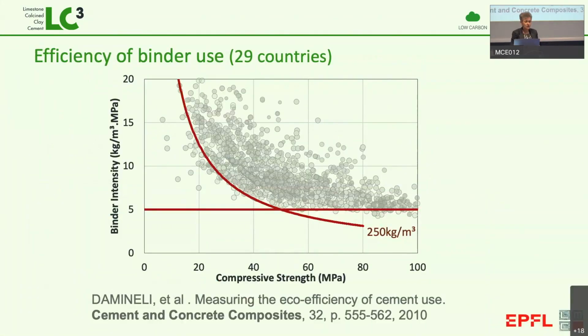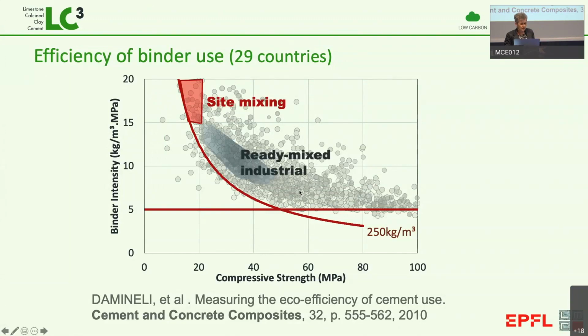And this graph here shows you a compilation of basically the cement content of concretes according to their strength. And you see for exactly the same strength concrete here, you can have one that uses this amount of cement and one that uses this amount of cement, which is like 3 or 4 times more. So bad concrete technology can waste much more CO2 than using just pure Portland cement. And how do we get from these not very efficient ones up here to these more efficient ones down here? Well, the first thing is to look for industrialized processes.